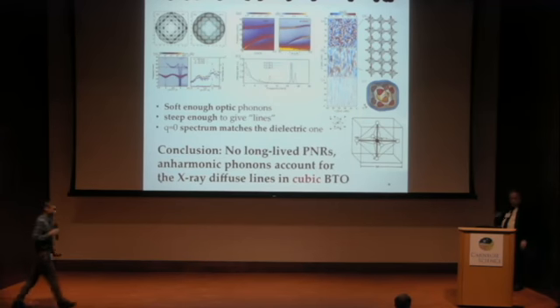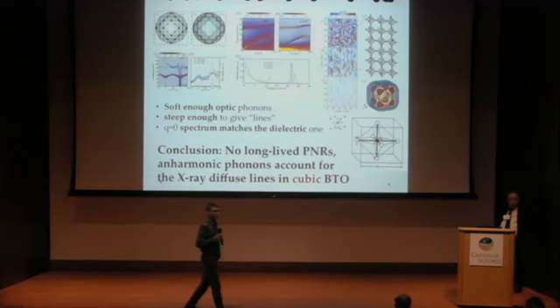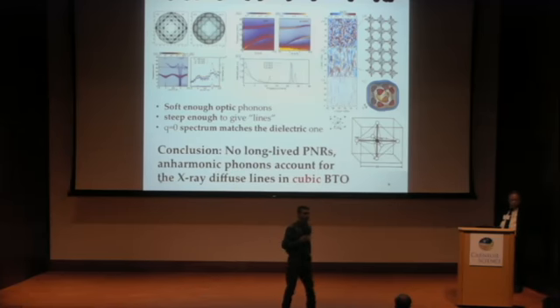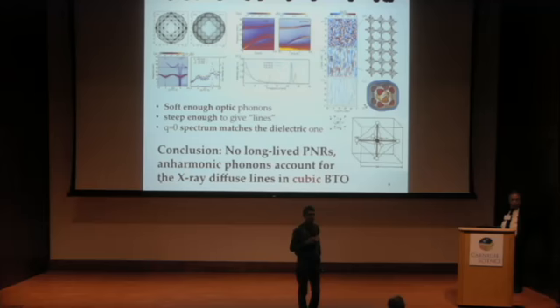Well, in a similar vein, we did similar simulations and went very, very close to TC. Even barium titanate, of course, is first order, but you still have fluctuations. It's very interesting that if you're in the fluctuation interval, you get twists, you get incommensurations and all that sort of thing, but it's only limited to an extremely small interval just above TC. So the general conclusion, I agree with you. But if you go into the fluctuation interval, then you have these additional excitations, which are quite strong, but limited to about 1 degree or 2 degrees. Okay, I take it as a comment.